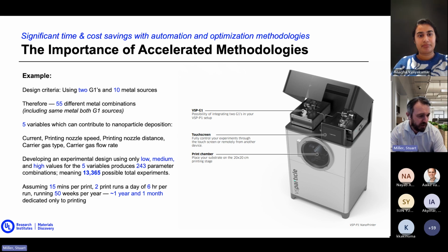presentation this morning. How much data do we need? If you looked at what we have at the moment, it is 2 G1 units that are on the nanoparticle. And at the moment we have about 10 metal sources. And these metal sources, if we take, for example, copper, we have 2 copper rods, one fitting in each of the G1 units. So it could give us a possibility of 55 different combinations of these metal sources. Could be copper, copper, could be copper, silver, silver, gold.